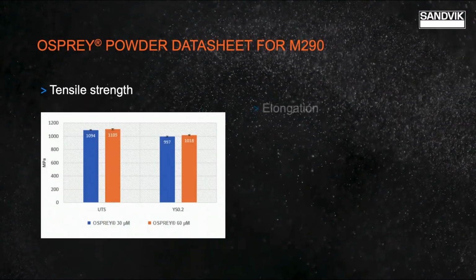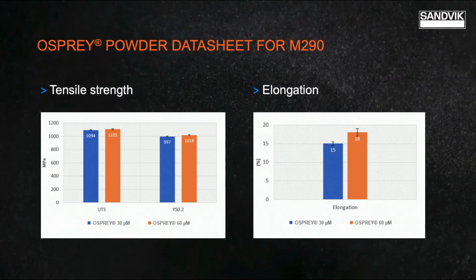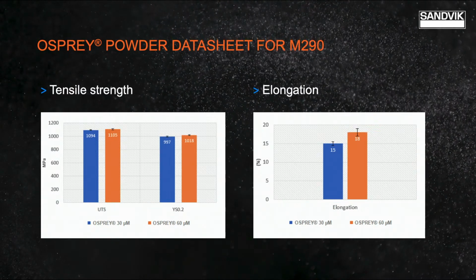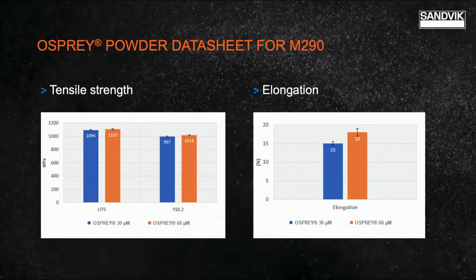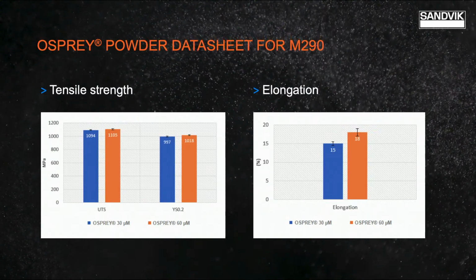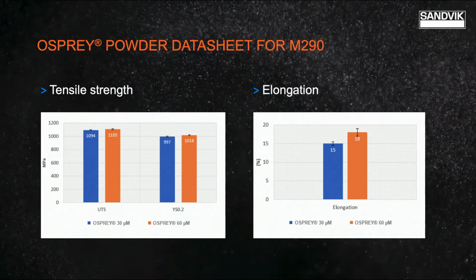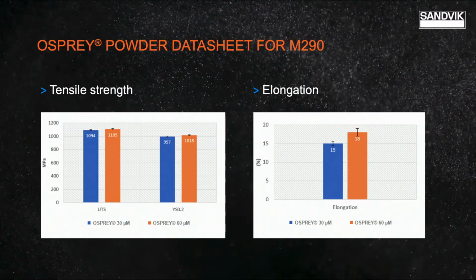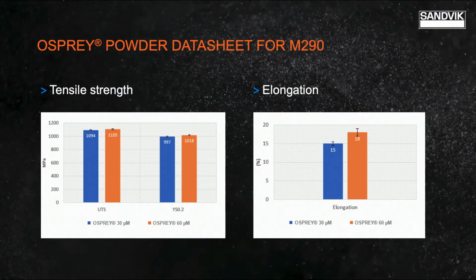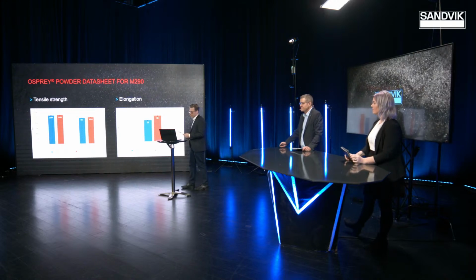That's very reassuring to hear. And now I wonder if this trend will be repeated if our customers want to speed up their processing time and print using, for example, 60 micrometer layer thickness. Can you show us something about this? Yeah, absolutely. We see one example of that in the next slide, when we compare a 30 micron layer to a 60 micron using the same machine, in this case the EOS M290, we can achieve properties that are just as good or even better for the 60 micron, as you can see in both images that I'm showing. And these are key tensile properties that most of our customers want, such as the yield strength and the elongation. So yeah, there you have it. It's a very important message.